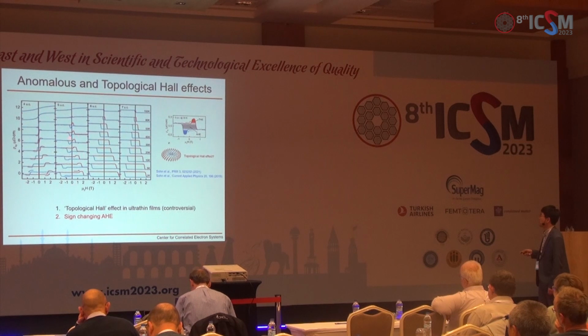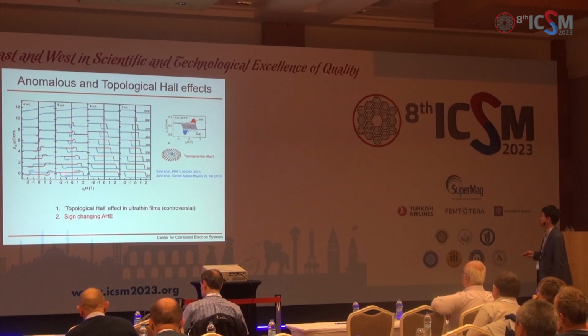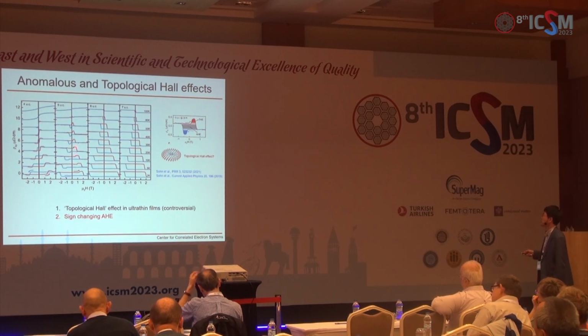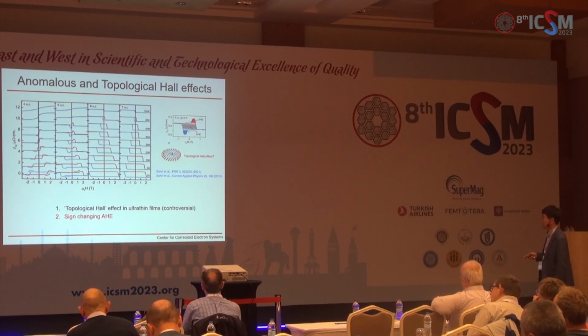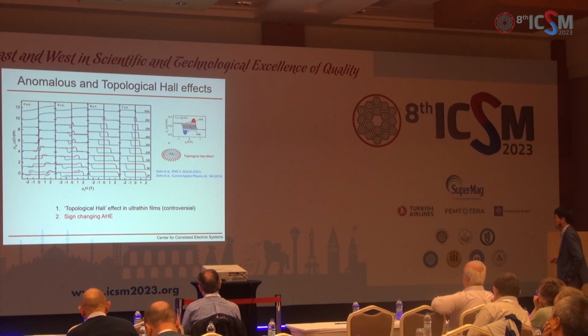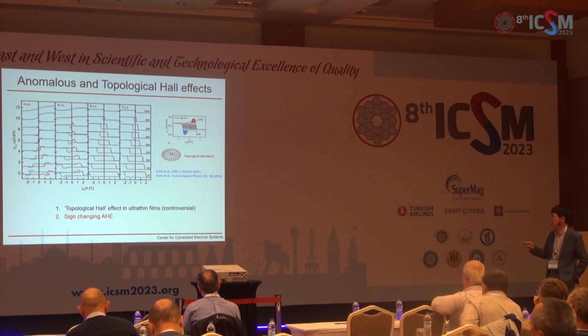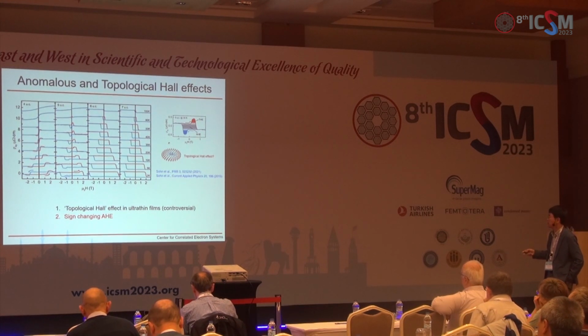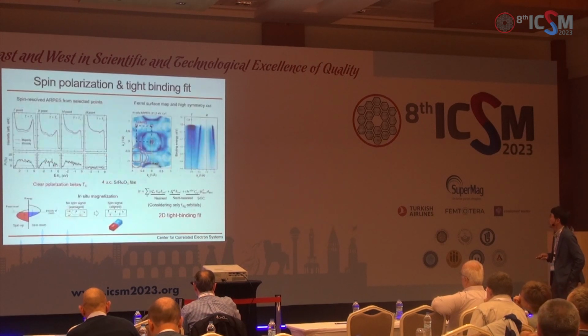If you look at this 5 unit cell data, you start with minus sign, but as you increase the temperature somewhere, it actually changes sign here. So even within a single system, as a function of temperature, the sign of anomalous Hall effect also changes. So this is very peculiar, and that's similar to what was reported earlier.